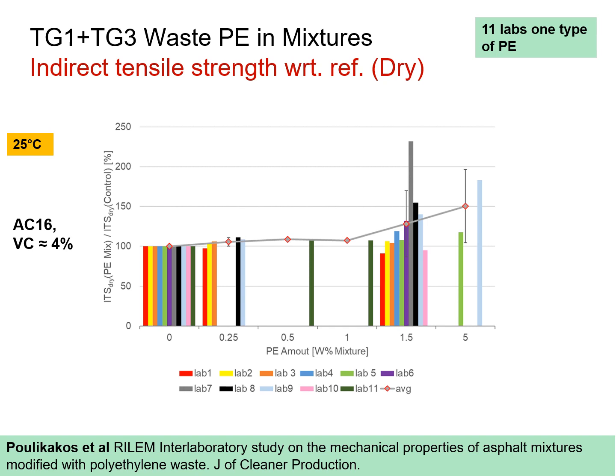So this example that I'm showing you here is looking at the indirect tensile strength in comparison to the reference strength in dry state. And you see this ratio as a function of the amount of polyethylene. And you see as the amount of polyethylene is increasing, it seems like the strength is increasing in comparison to the reference.